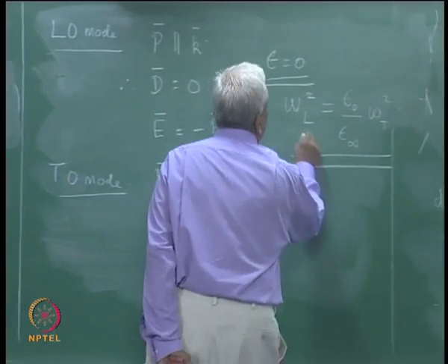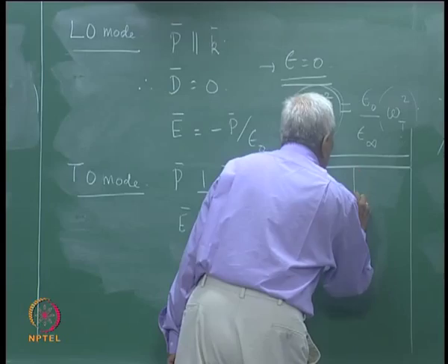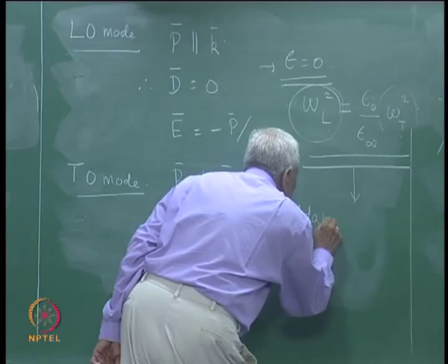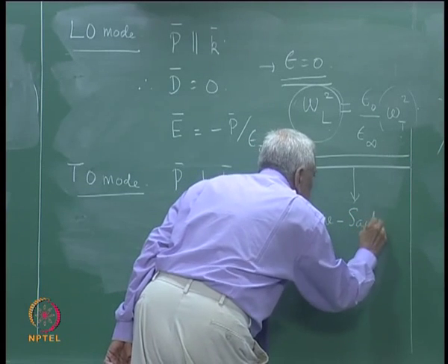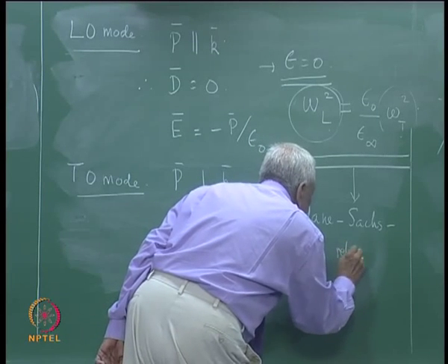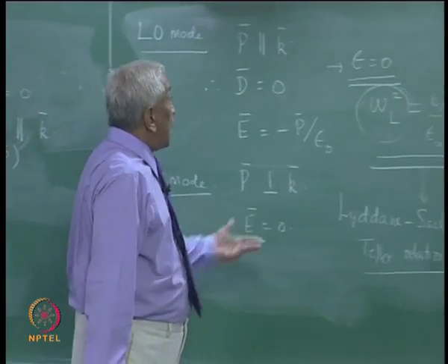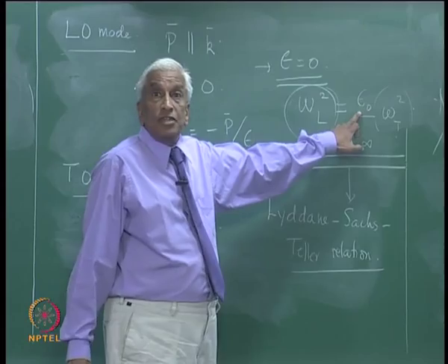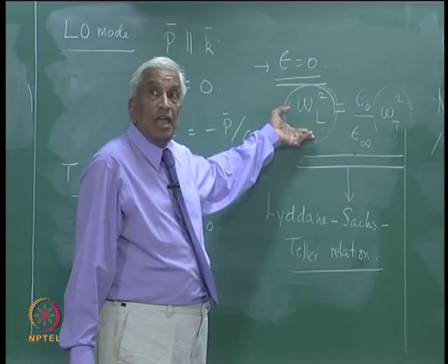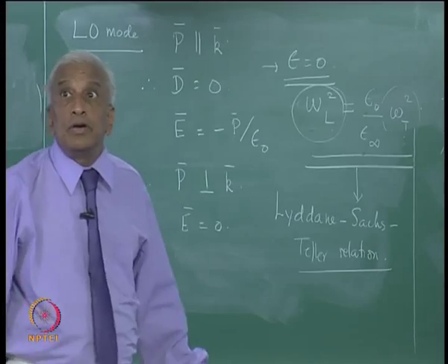So, this very interesting relation between the frequency of an LO mode and the frequency of a TO mode goes by a special name, the Lyddane-Sachs-Teller relation. This can be experimentally verified, because one can measure the static dielectric constant, the high frequency dielectric constant, and the angular frequencies of the LO and TO modes. Therefore, one can check this relationship.